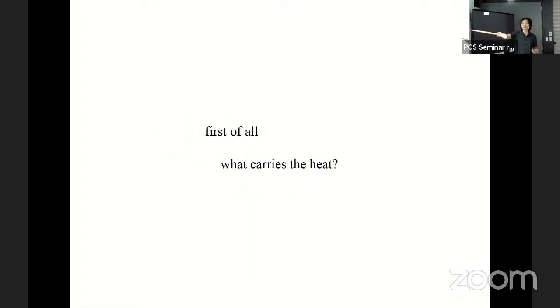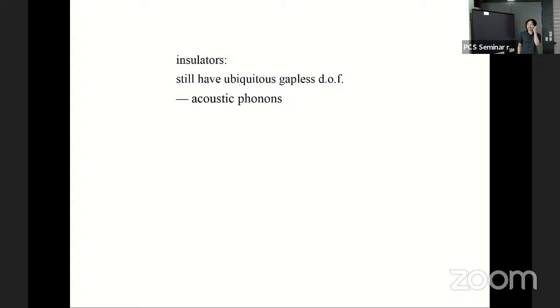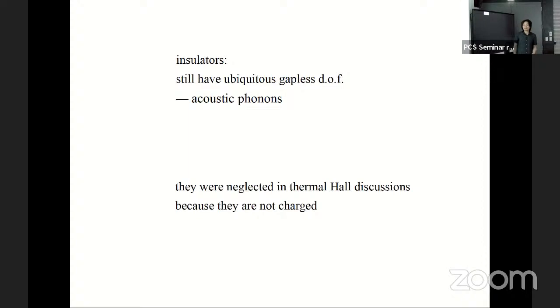So first of all, we want to confirm that it's the phonons that carry the heat. And why is that? There is a very good reason to think phonons are relevant, because in all these materials, which are gapped insulators, there's one ubiquitous gapless degree of freedom, which is the acoustic phonon. And as we said, they were neglected in thermal Hall discussions because they are not charged. So the contribution is very tiny, like in sodium chloride, 10 to the minus 10 Hall angle. And in the STO experiment, the effect has been quickly attributed to the phonons, both by the experimental team and by us, and I'll explain why soon.